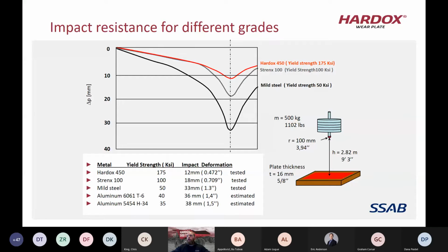We actually have a drop test rig that has been built and that we use in Oxelösund, Sweden. We have plate samples that we put into the rig. You can load a certain amount of weight onto it, and then you drop it from a set height. So we can actually measure the dent depth that we see, and see if the plate would crack, depending on the amount of impact that the plate would sustain.